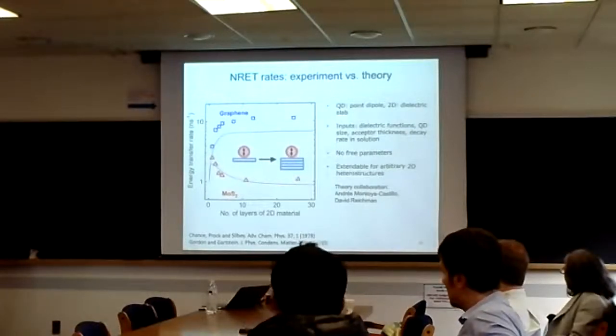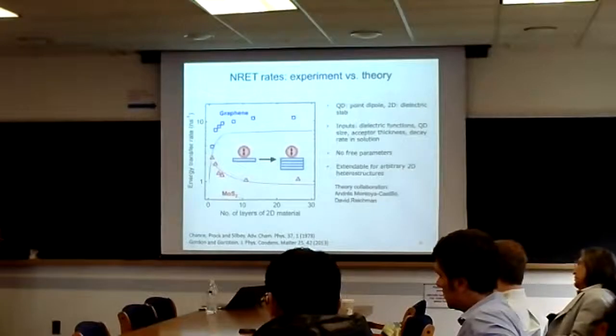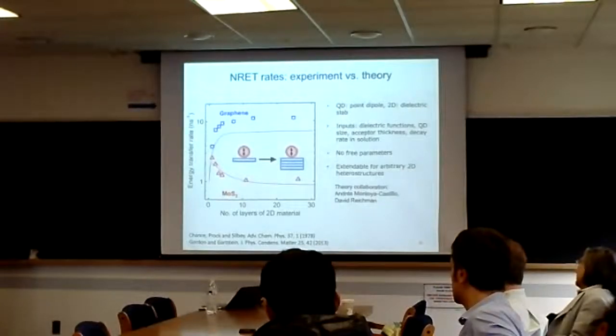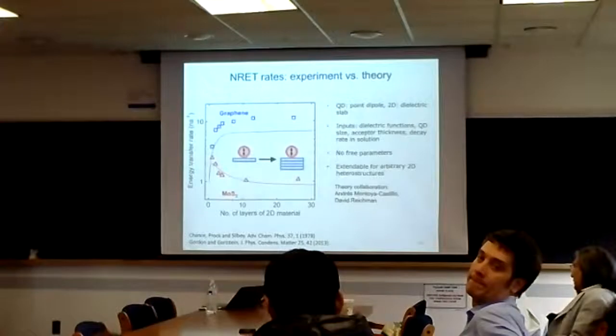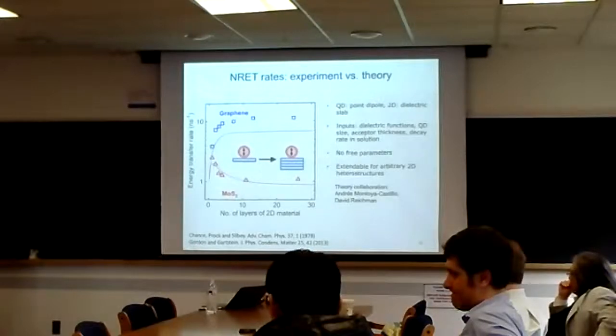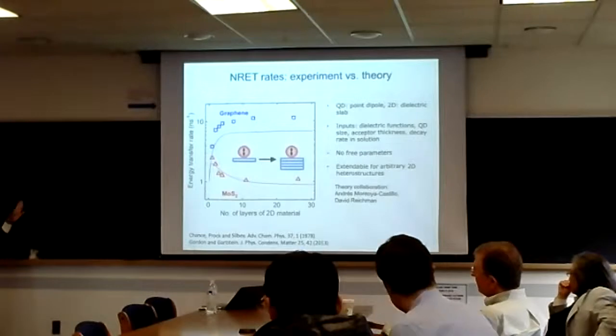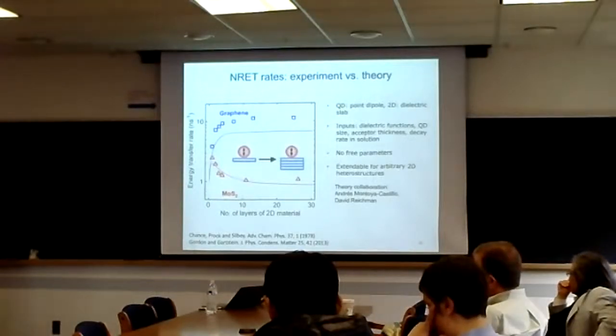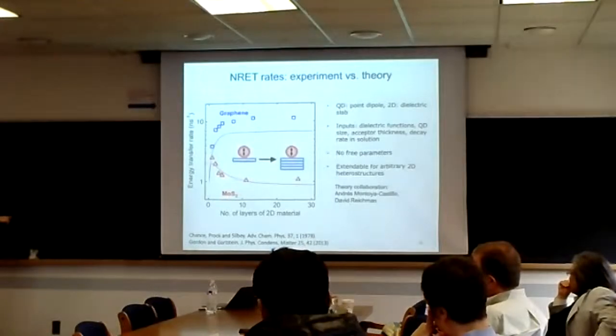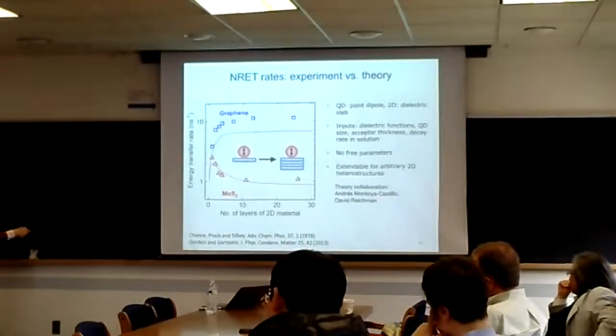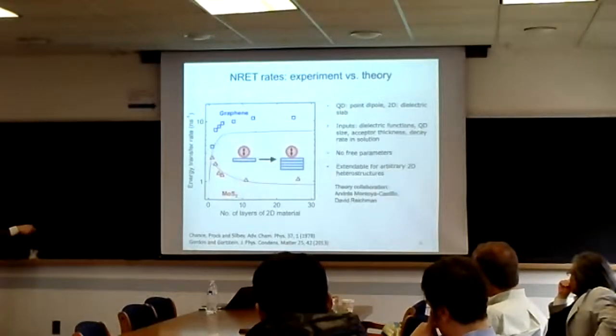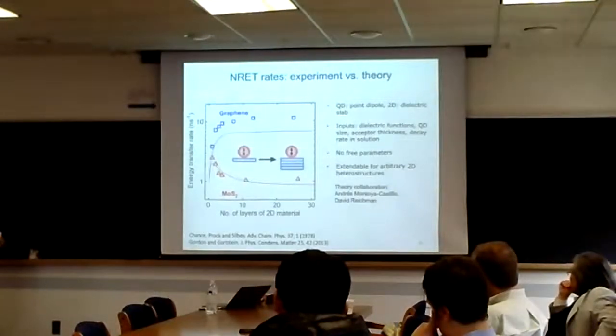Because we did the simulations for it as well as the analytical form. If you had a uniform dielectric, say of this epsilon of MoS2, you're just embedding the whole thing. But remember, the dielectric of MoS2 around is huge. But so is the imaginary part here, right? So the dissipation is winning overall. And the reason the radiative rate is not changing as much is because it's really anisotropic. You're only seeing it on one side, and this is also embedded in like 10 nanometers of zinc sulfide or something like that. So by the time it sees the change here, it's a much weaker change in the overall effect.